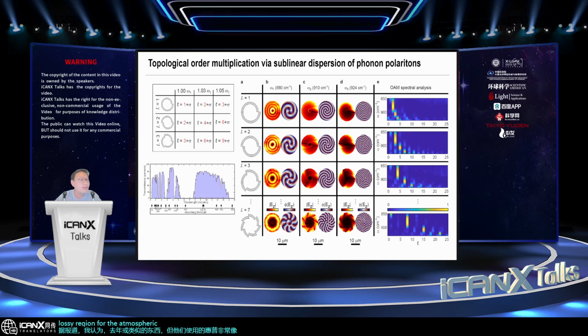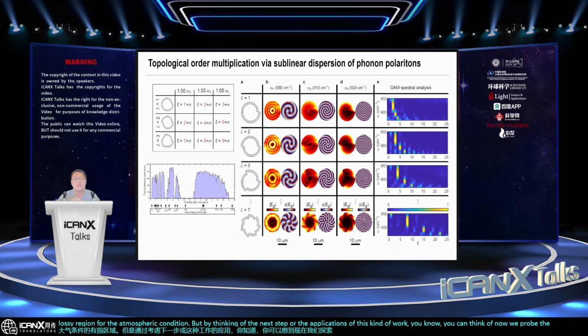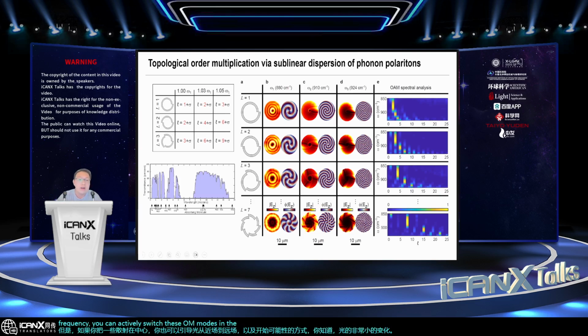But by thinking of the next step or the applications of this kind of work, you can think of now we probe the modes in the near field, but if you put some scatterers at the center, you can also guide the light from the near to the far field. And with that possibility, with a very small change of the frequency, you can actively switch these OAM modes in the far field. That could be potentially useful, which we work with silicon carbide.